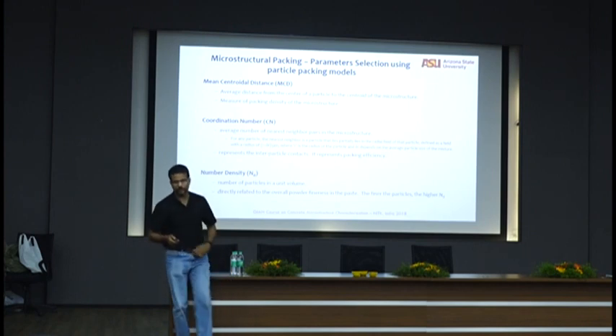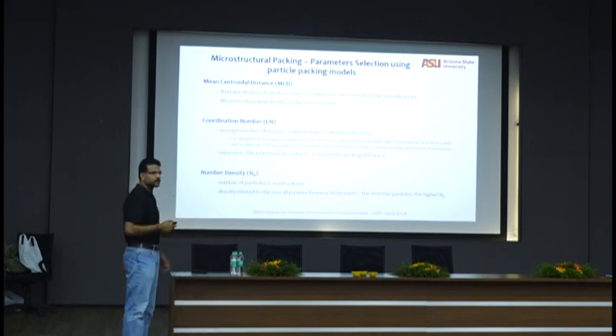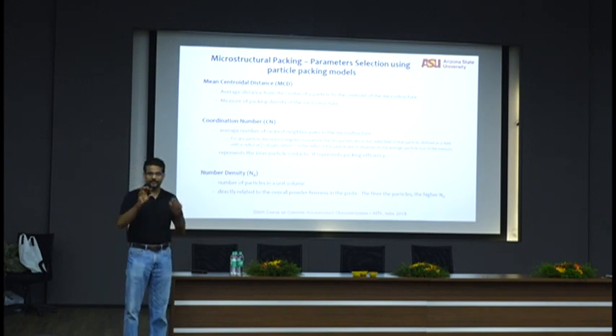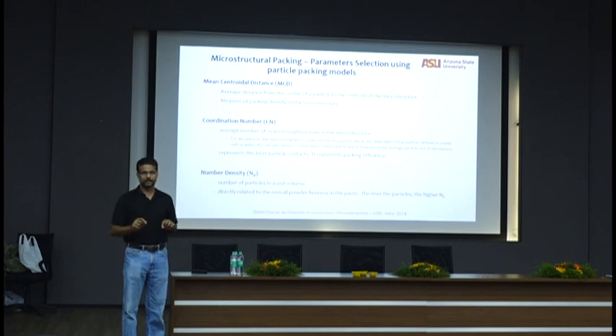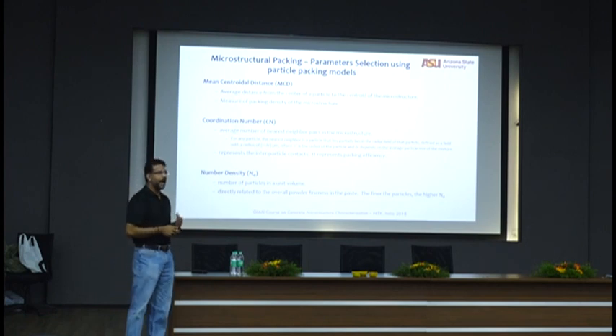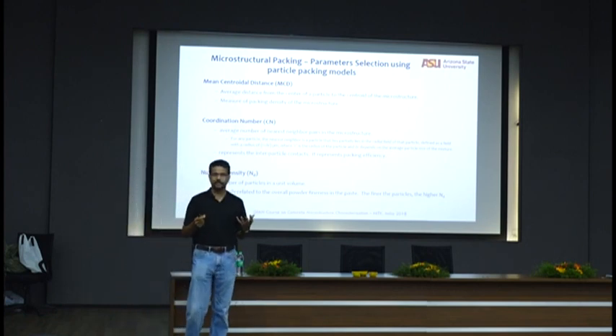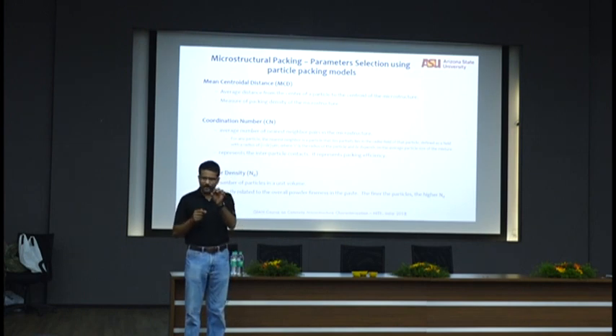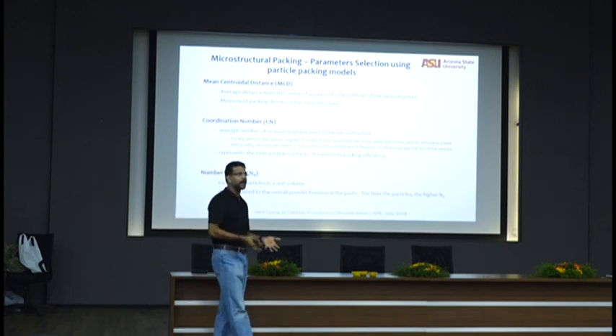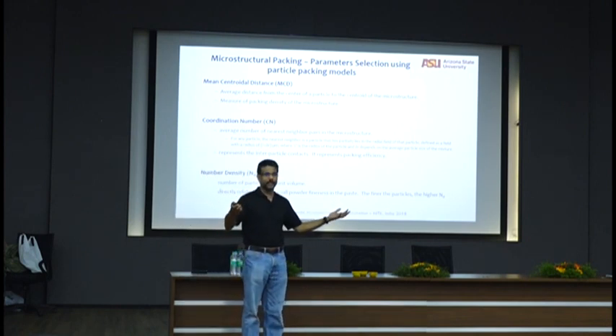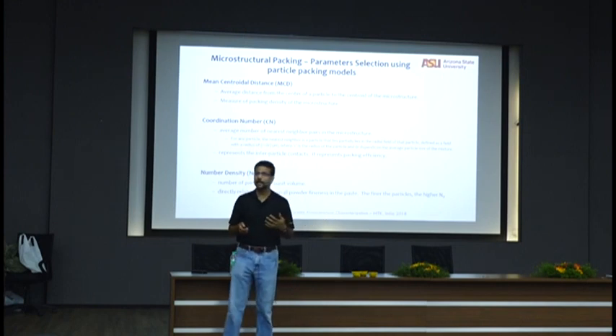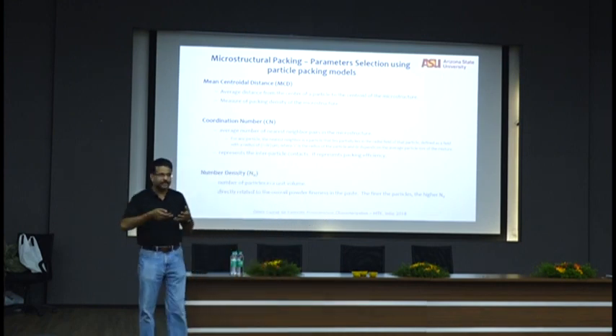Then we come up with 3 different parameters of the microstructure. The first one is called the mean centroidal distance. If I have 2 particles, what is the distance between the centroids of both particles? You measure the distance between centroids of all the adjacent particles in the microstructure and come up with one representative mean centroidal distance. If I have really small particles, they will be close to each other, so the mean centroidal distance will be lower. If I have large particles, the mean centroidal distance will be larger. So this distance gives you an idea of the distance between particles.